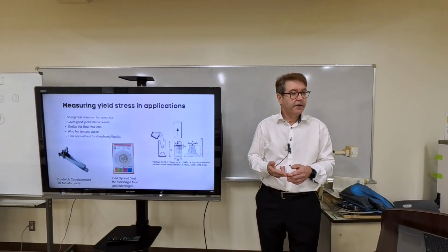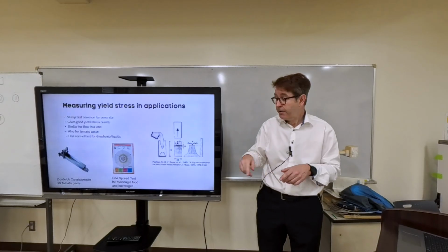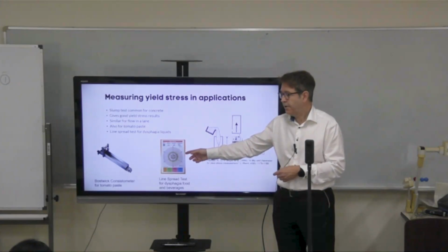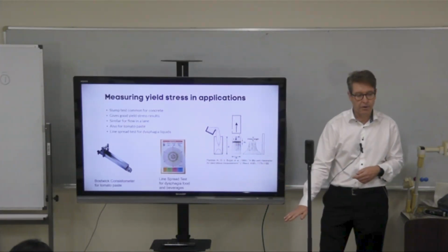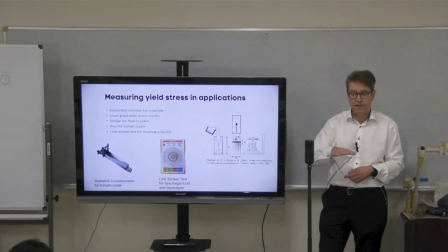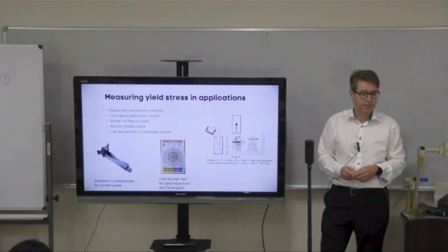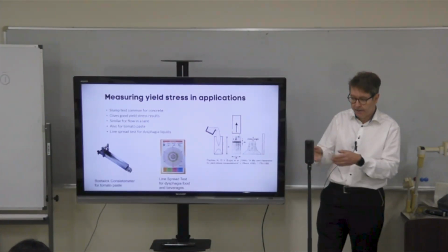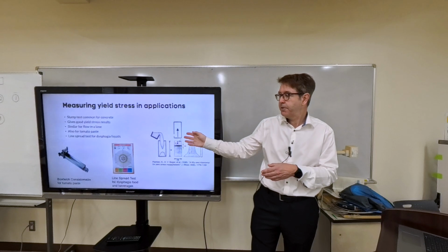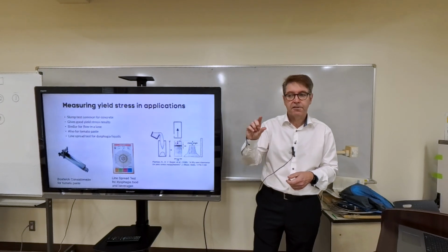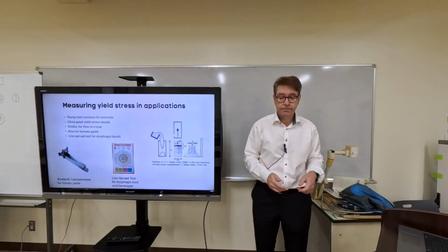So you get a sum of all these as a measure, because you measure it in centimeters. But it works because the yield stress is usually very low and the density is very similar. So it mainly measures viscosity. But if you would come up with another thickener that has a higher yield stress, it would give very strange readings. So you always measure a sum of a lot of parameters.